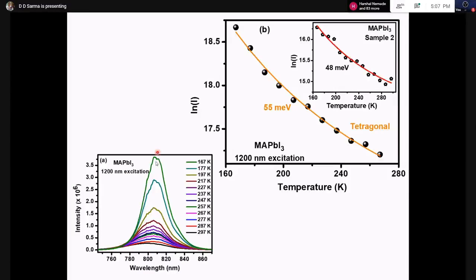And then you can plot the intensity variation. Then you can fit it to an equation, and therefore you can extract the excitonic binding energy. Reliable excitonic binding energy, different samples, different times. One is 55 millielectron volts, another is 48 millielectron volts, typically telling you what the error bar is on these measurements.